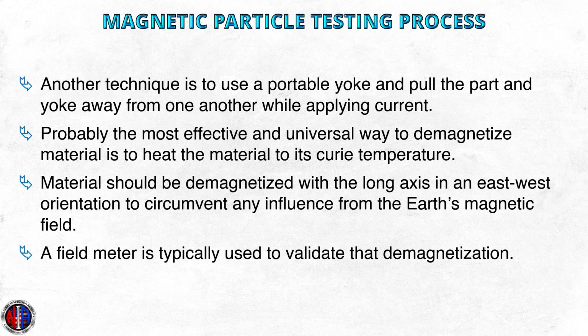As a final note on demagnetization, material, especially very long parts, should be demagnetized with the long axis in an east-west orientation to circumvent any influence from the Earth's magnetic field. A field meter is typically used to validate that proper demagnetization is successful by verifying the removal of residual flux. Most specifications and industry standards require magnetic flux to be less than 3 Gauss after demagnetization. It is always desirable to demagnetize circularly before longitudinally. As a reminder, circular magnetism cannot be detected with a field meter.